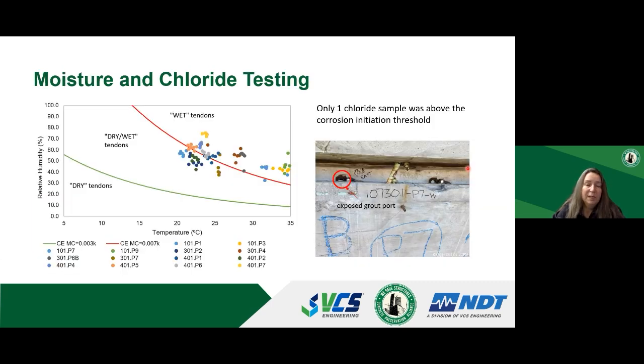We also performed moisture testing. Here we pushed dry air from one end of the tendon to the other. As you can see on this chart, the majority of the tendons were in the dry-wet or wet condition, which puts them at risk for corrosion. The chloride samples of the grout showed that the majority of the samples had chloride concentrations below the corrosion initiation threshold, and only one sample had a high chloride concentration. This was because the pour back actually didn't cover the grout port at that location. It was left exposed, and chloride contaminated water from the deck ended up getting in there.